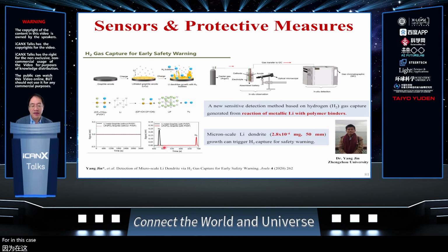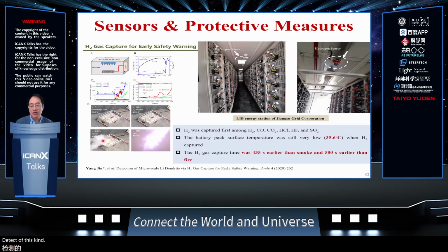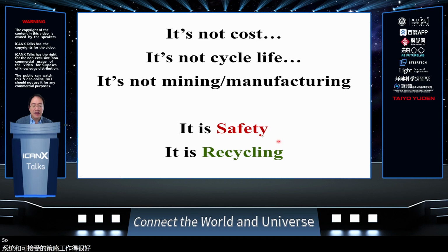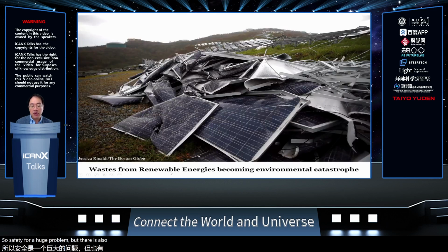But in this case, Jin Yang used a hydrogen sensor, and that was able to detect this kind of thermal runaway phenomenon 400 seconds, so this is like 8 minutes, before there is any smoke or even any heat signature on the battery cell. And so this has now been installed in container-scale systems, and it has been demonstrated to work quite well. So safety is a huge problem, but there is also a problem with recycling. And in fact, this is really a very big problem, because a lot of the renewable energy waste ends up not even properly incinerated, and it just ends up in landfills, very often in developing countries.